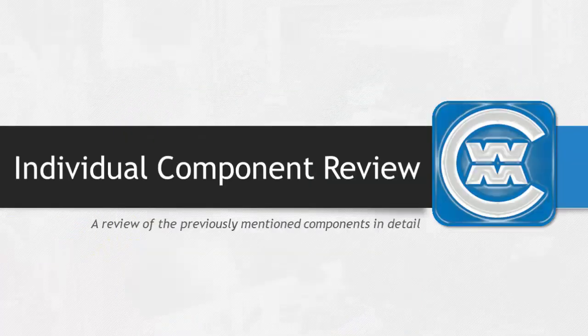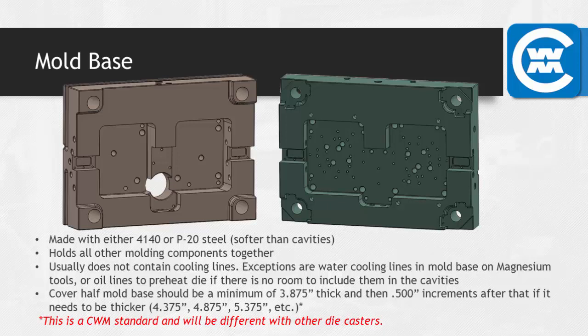Okay, moving on to the individual components associated with the die. So the mold base is responsible for containing the cavities and providing enough material around the cavities to contain all the molten metal under pressure. The mold base is softer than cavity steel to allow for slight deformations under clamping pressure, and as it says here, the mold base does not usually contain water or oil lines, but it can in some cases. Most of the holes you see here are clearance holes to allow pipes access directly to the cavities, and this allows water and oil fittings to be outside the die where the caster can access them if necessary. The last bullet point describes a CWM specific standard due to the design of our cold chamber shot well system. This isn't something a customer needs to be concerned about on a new die, but it would come into play on transfer tools.